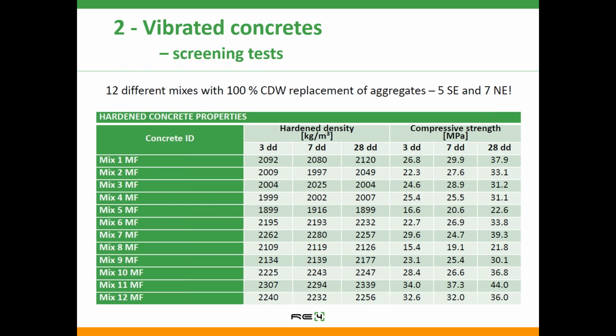So moving on to the second type of concrete, which is the vibrated concrete. Again, some initial screening tests were done with 100% replacement with recycled demolition aggregates. The compressive strengths that were achieved varied from very low, 20, to over 44 megapascal. Hardened densities are affected if you have masonry particles in the recycled aggregates, so strengths and densities are related.